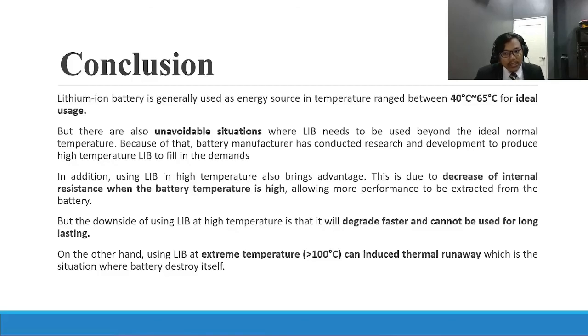This is due to the decrease of internal resistance when the battery temperature is high, allowing more performance to be extracted from the battery. But the downside of using a lithium-ion battery at high temperature is that it will degrade faster and cannot be used for long. And on the other hand, using a lithium-ion battery at extreme temperature can induce thermal runaway, which is the situation where the battery destroys itself.